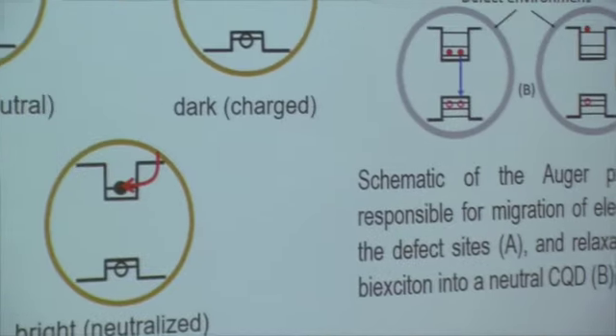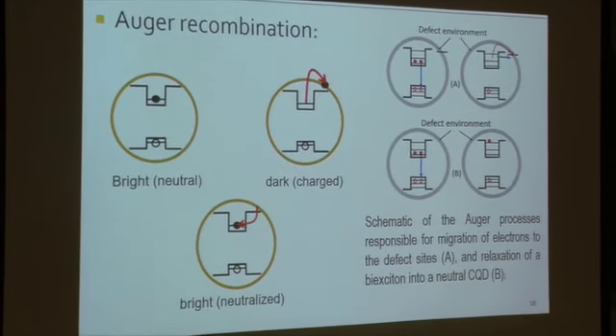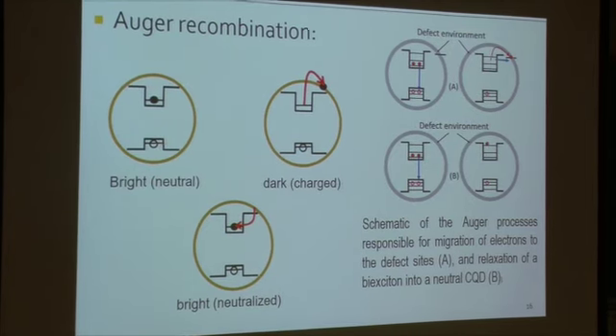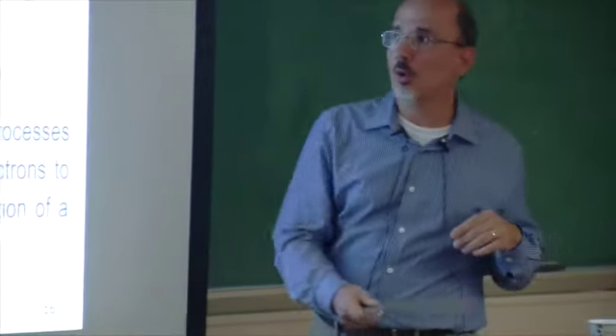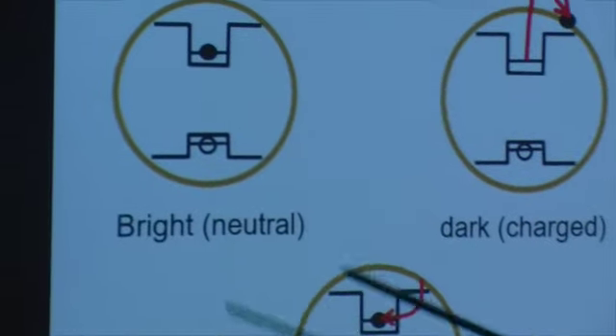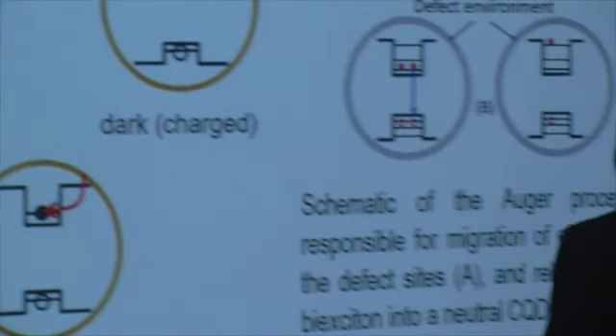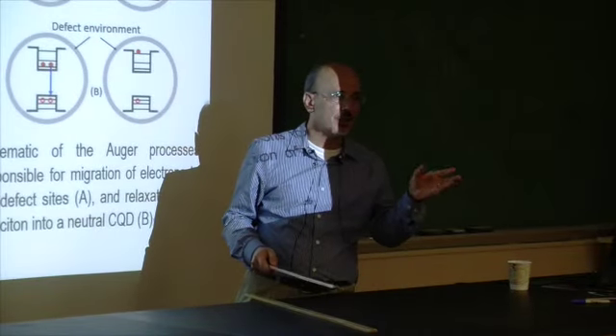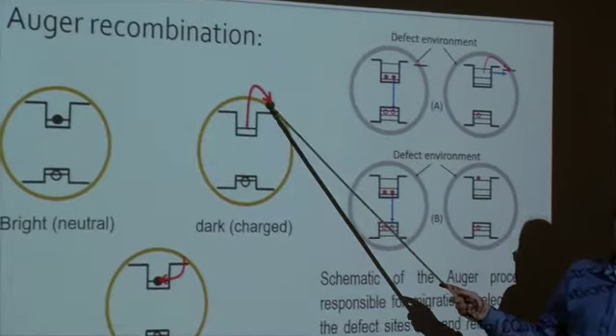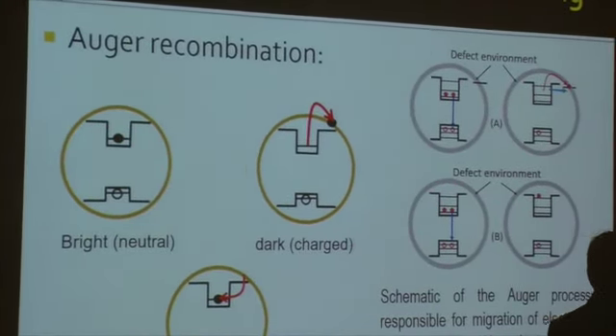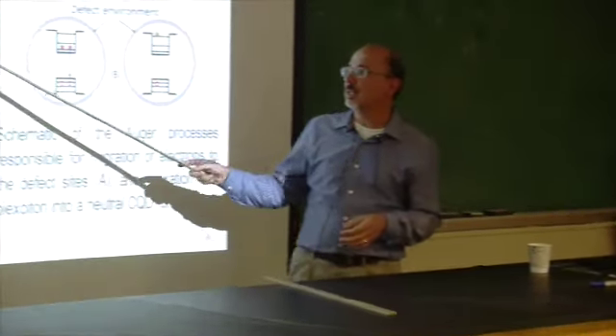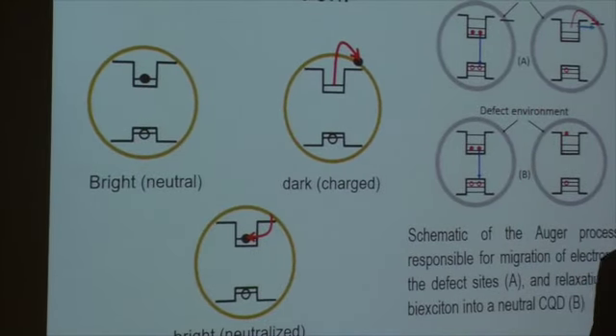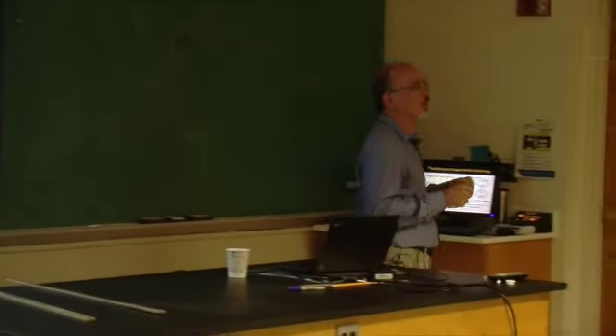If you ask where it is coming from, why single quantum dots blink, the common theory is this: you continuously excite a quantum dot with the laser, you don't turn your laser off and on, yet sometimes it becomes dark although you continue to excite it. Why does it become dark? The idea is about Auger recombination. When you have one electron and one hole, you basically have a bright state. But if the temperature is high enough, an electron can get trapped in a trap state, of which plenty are available in a normal quantum dot. Once trapped, there is only one carrier there. If you excite it with another photon, you generate one electron and one hole, and then you get Auger recombination.